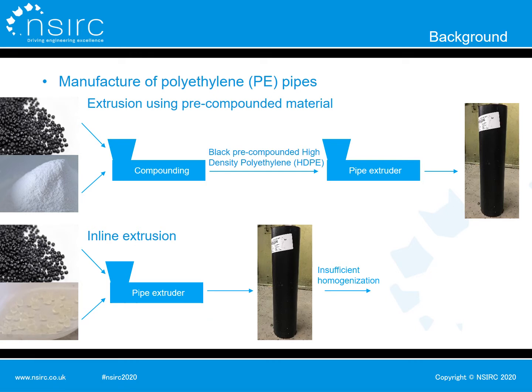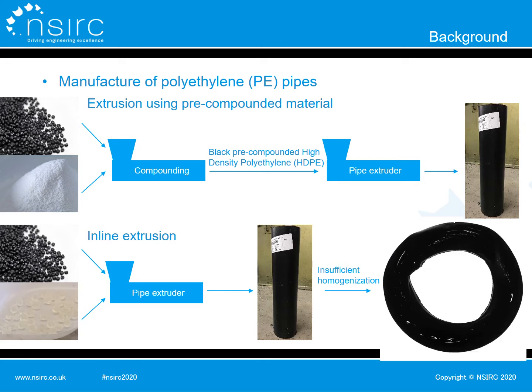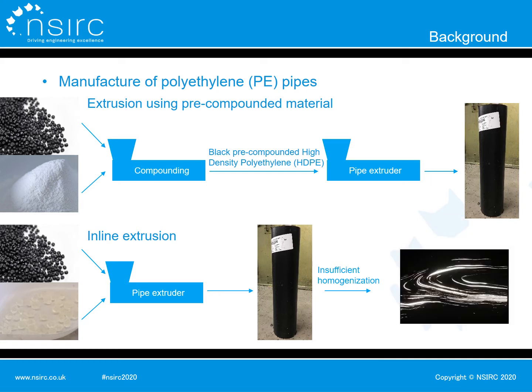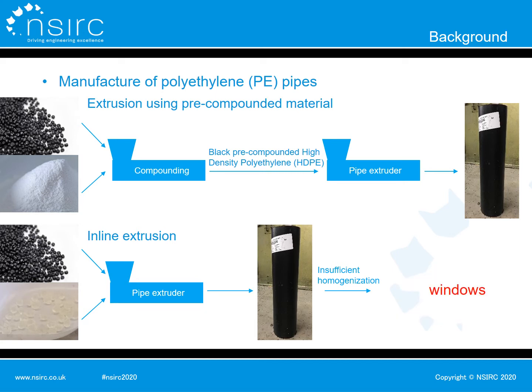Although the pipe made by inline single-screw extrusion may seem totally black by naked eye, when cutting a thin layer from the pipe end, some white regions can be seen. If we magnify and focus on one small white region, we can see some white striations or swirls with no carbon black, and black regions with high carbon black concentration surround the white striations. These white striations are called windows.